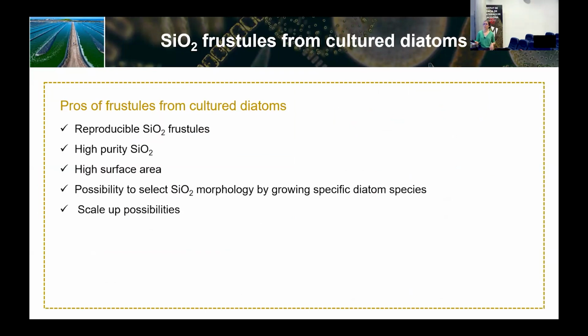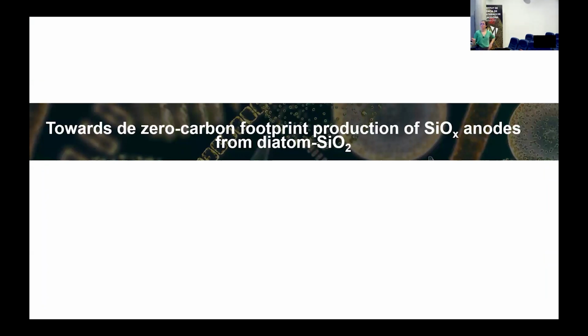So the pros of this is that we have reproducibility, higher silica content, and high surface area, so we don't need to do ball milling to increase it. We can select the silica morphology by selecting the diatom species, and we can scale this up because this is already happening in an industry. So the material is already being produced with high reproducibility at an industrial scale. So now we want to go to SiOx.